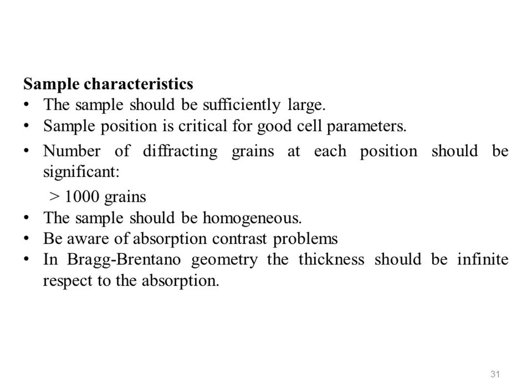Sample characteristics. The sample should be sufficiently large and the beam should be entirely inside its volume, meaning surface. Sample position is critical for good cell parameters along with perfect alignment of the instrument. The number of diffracting grains at each position should be significant, greater than 1000 grains. Remember that only a fraction is in condition for diffraction. Higher beam divergence or size increases this number. So the sample should have millions of grains in the diffracting volume.